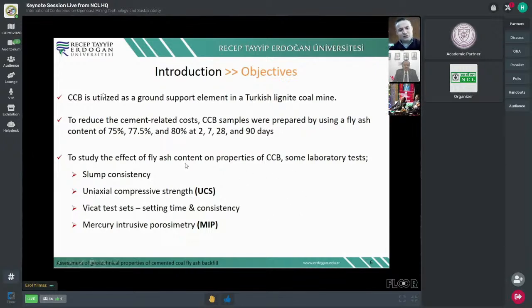So to reduce the cement related cost, we use 75%, 77.5%, and 80% of fly ash. And also we got some different curing times, 2, 7, 28, and 90 days. Our intention is to study the effect of fly ash content on slump consistency and the uniaxial compressive strength, Vicat tests like setting time and consistency, mercury intrusion porosimeter. Here